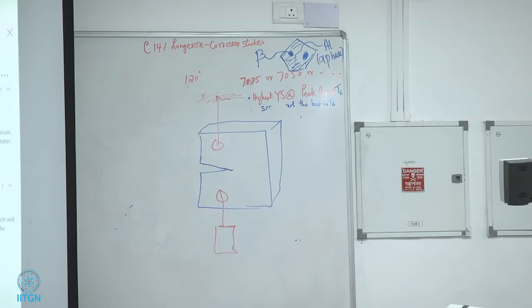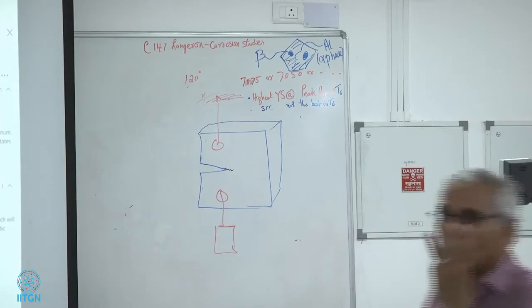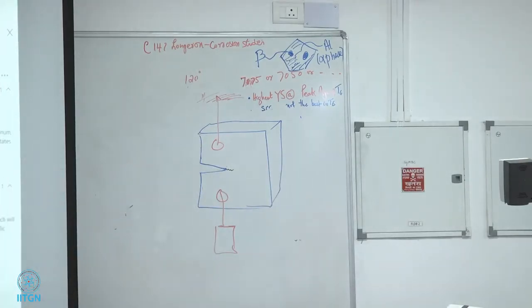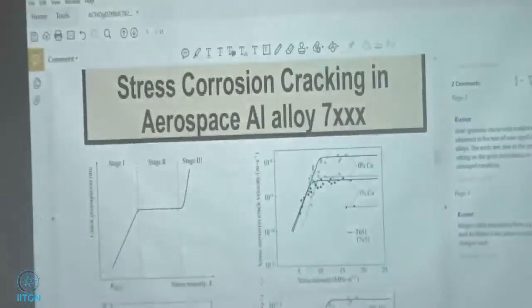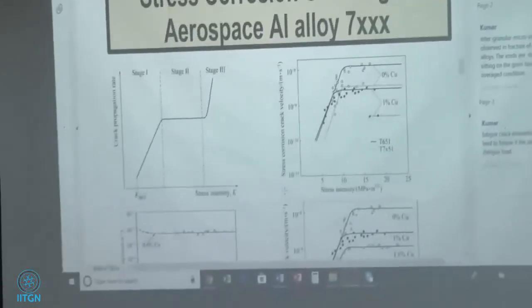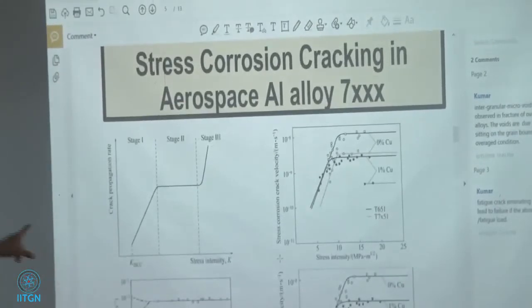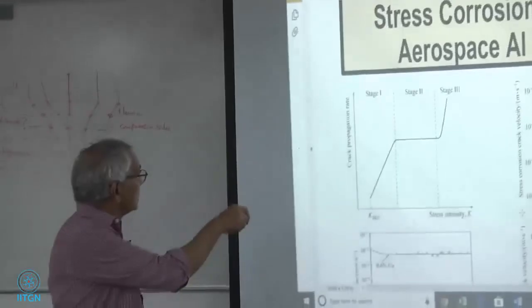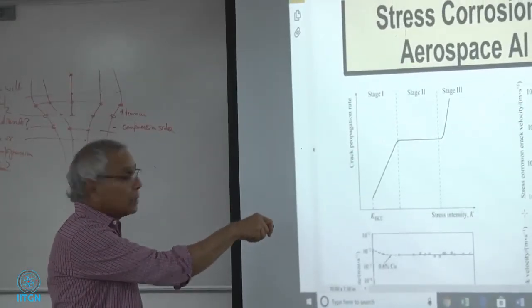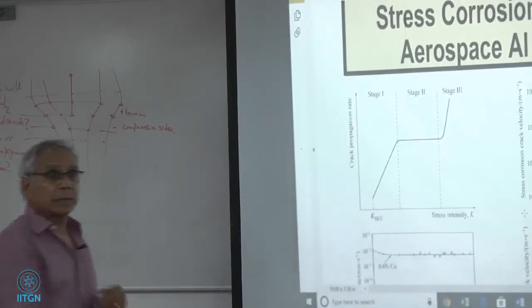Normally the books will tell you that you're supposed to get 3 regions. Region 1, stage 1, and region 2, the plateau region. The crack is still moving, but da/dt is constant. So if you plotted a versus time, the crack is still moving, but the slope is a constant growth rate. And this is stage 3, fast crack growth rate. Ideally, this is what is supposed to happen.